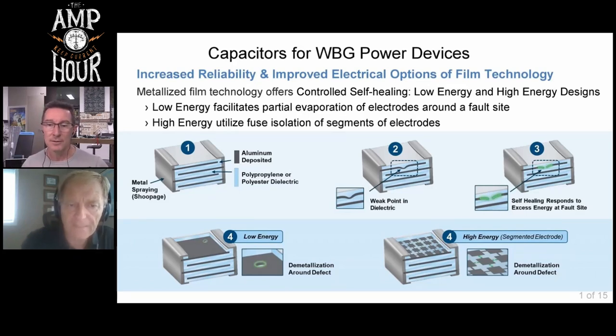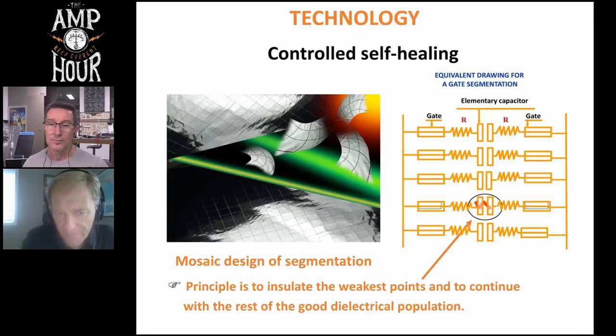Within films, it's difficult because if you don't get self-healing correctly, it could very well have an early failure. So that's something to be cautious of. Usually the industry is getting much better with that. I would say in the old days, it was well over half being caused by that early wear out. I think it's probably switched. So it's probably moisture. Probably moisture. There you go.